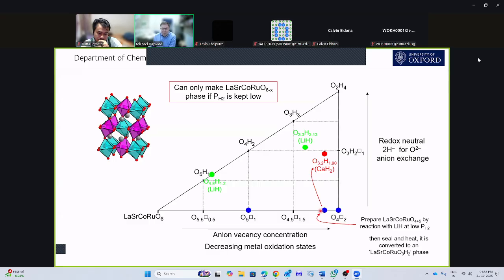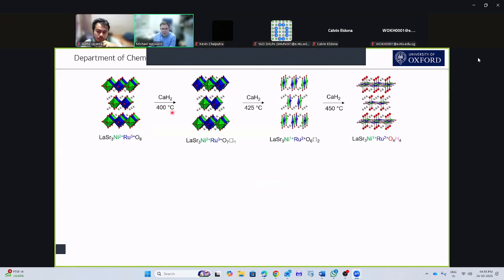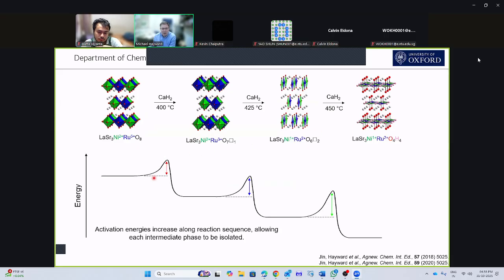And what that means for the activation energies is, if we think about the case where we see the reduced oxide intermediates, what it shows is that the activation energy for sequential reactions is getting larger and larger and larger. And so if we add 400 degrees, we get over this barrier, but we stop here. Increase to 425, we get over that barrier, but stop here. And then increase to 450, we get over that barrier to make the final product.